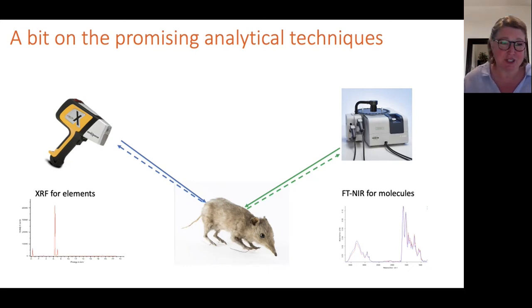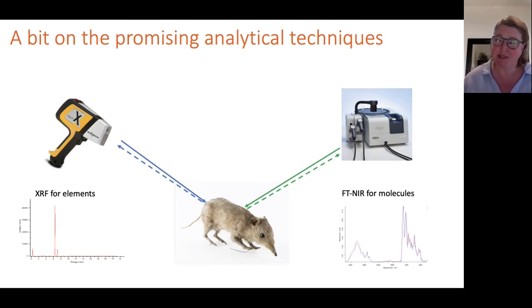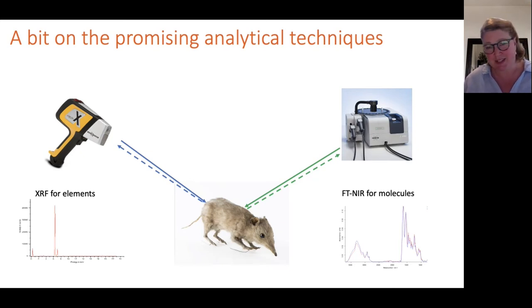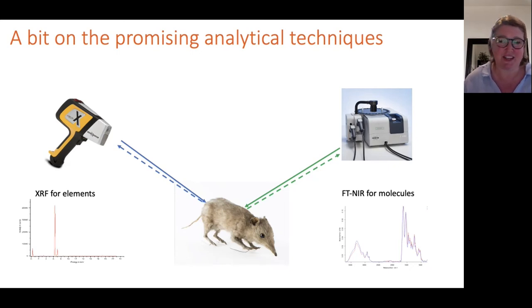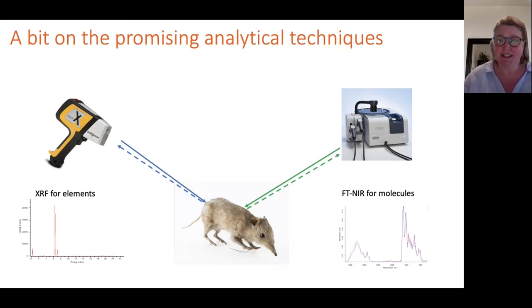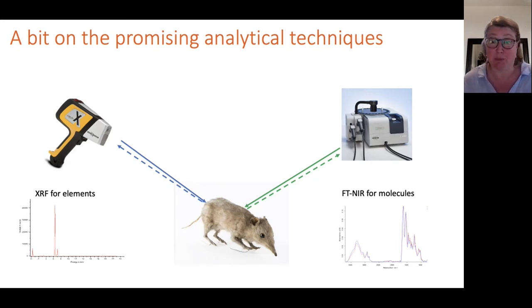The Fourier transform near-infrared technique emits infrared light that causes the bonds within molecules to begin to vibrate, and in doing so the molecular bonds absorb some of that light energy. The instrument detects this change and outputs a graph showing a unique fingerprint that can be used for identification and characterisation of the chemical structure within the specimen. The two techniques work well together: XRF is particularly useful for inorganic components and the infrared technique for organic components.